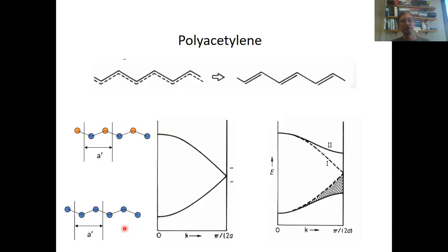Well, as we localize the pi bonds, a band gap opens. One of the two crystal orbitals, which are completely non-bonding in this case, becomes bonding, and the other one becomes antibonding. So we have overall stabilized our electrons because our band is only half filled, and we can fill all the electrons into the bonding crystal orbitals. So that explains the localization of the pi electrons.